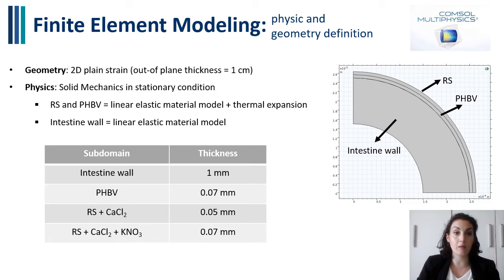Then finite element modeling was performed in COMSOL Multiphysics in order to analyze the capability of the developed tube to contract under thermal stimuli and compress the intestine wall. A solid mechanics module in stationary condition was used, and more in detail, for the tube that is composed of two layers, a linear elastic material module with the addition of the thermal expansion module was used. Differently, for the intestine wall, only the linear elastic material module was implemented.